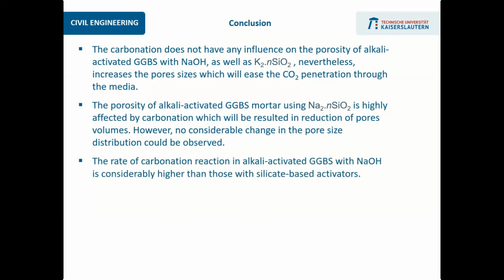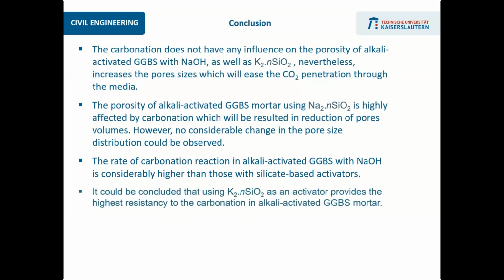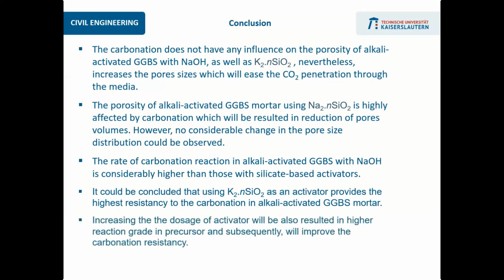The rate of carbonation reaction in alkali activated GGBS with sodium hydroxide is considerably higher than those with the silicate based activators. It could be concluded that using potassium silicate as an activator provides the highest resistance to carbonation in alkali activated GGBS mortar, and increasing the dosage of activator will also result in a higher reaction grade in the precursor and subsequently improve the carbonation resistance.